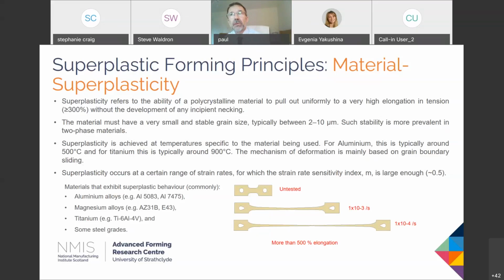What these materials will all have in common is that they have a very fine grain size. They're being carefully processed through the various sections of the rolling mills to generate a grain size of 10 microns or less. That's the sort of target that we aim for. And basically, in that context, the finer the grain size, the better. The reason that's important is because the grain boundaries play a big part in the actual mechanism of superplastic deformation. I won't go into that anymore, but if anybody wants to talk more about that, we can pick that up at the end.